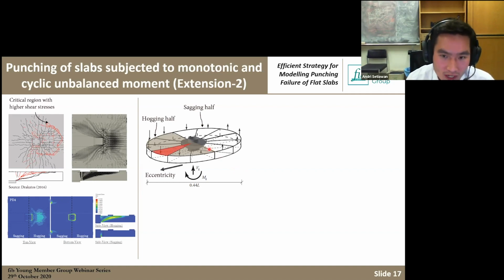For the cyclic one, because we know that with the repetitive cyclic loading, we have a plastic accumulation of rebar strain, the crack width will be higher. So the redistribution physically will be less. So what we did is that we assume no redistribution at all. So when the first joint at this red hatch region fails, we assume that, okay, the connection has failed. So this is how we distinguish the behavior of monotonic and cyclic loading of the slab.